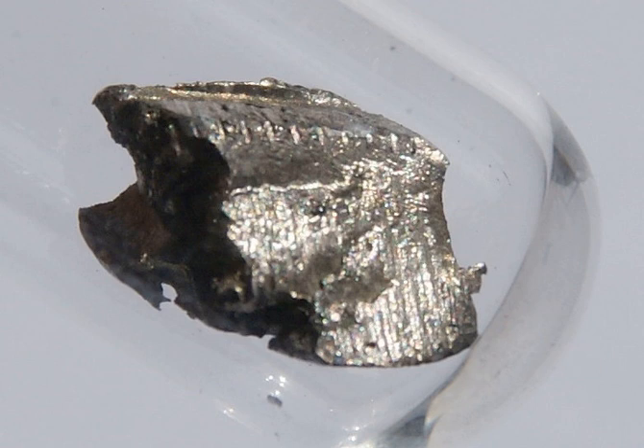The procedure for monazite, LnThPO4, which usually contains all the rare earths, as well as thorium, is more involved. Monazite, because of its magnetic properties, can be separated by repeated electromagnetic separation. After separation, it is treated with hot concentrated sulfuric acid to produce water-soluble sulfates of rare earths. The acidic filtrates are partially neutralized with sodium hydroxide to pH 3-4. Thorium precipitates out of solution as hydroxide and is removed.